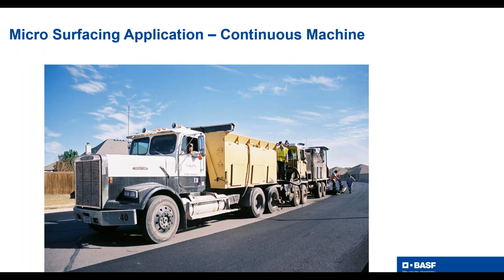Here's an example of a continuous machine. Because this mix can cure fairly quickly, the machine can place down, and if you're in an area or a highway or an interstate where this material can be applied, it can go down without the machine being stopped. And they call it continuous because you have this truck in the front, it's called a nurse truck, and it can haul the aggregate, emulsion, and water. And the water and emulsion hose will be hooked as it backs in. The machine that's applying it never stops, and the product can just be placed in a continuous manner without having to be stopped, as long as you have enough nurse trucks to feed it as it's moving down the road. So this is a very good process, especially for highways and interstates.